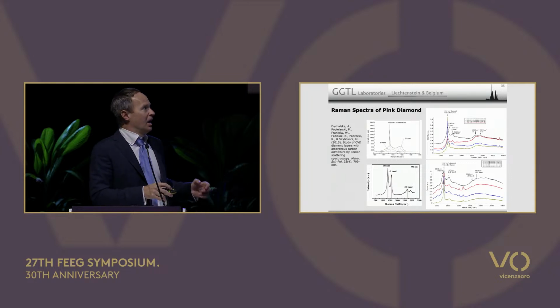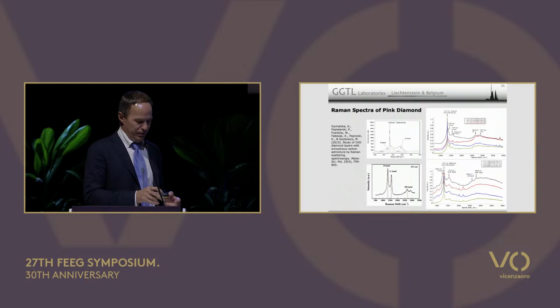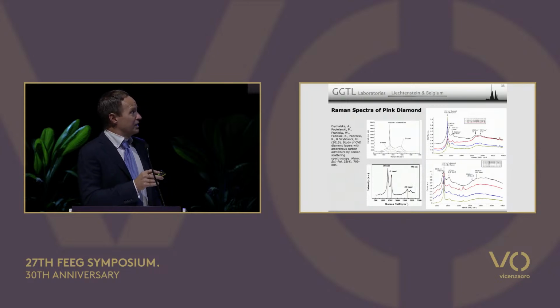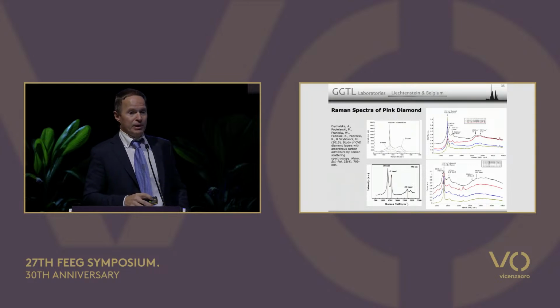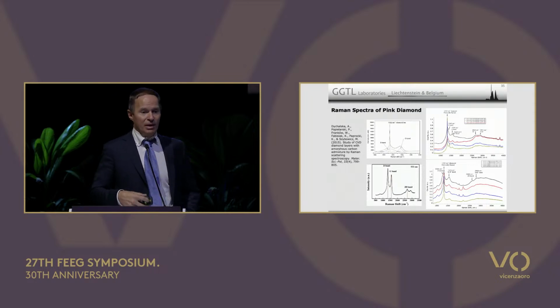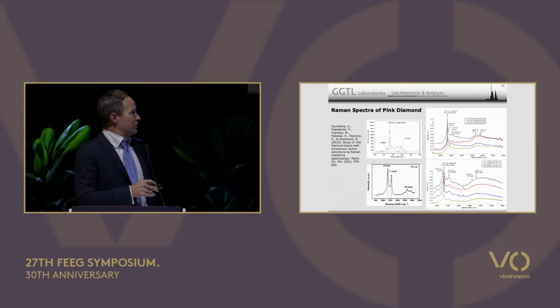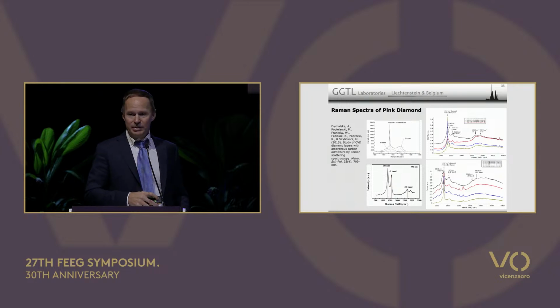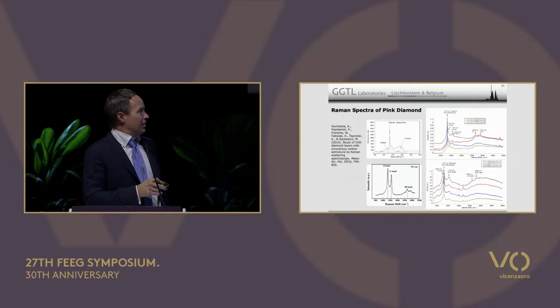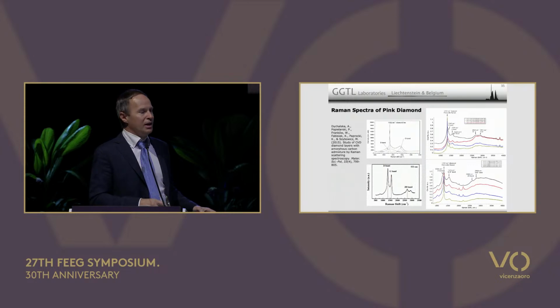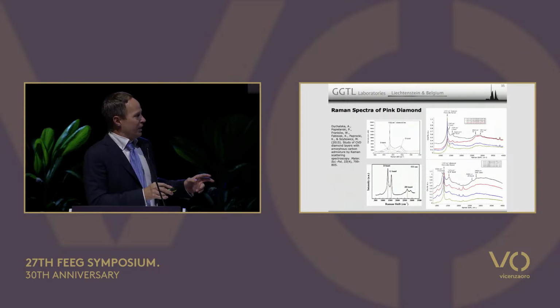Working through this and doing experiments at room temperature and low temperature, I came to the conclusion that what we're looking at here is not photoluminescence, but Raman signal. So these bands here and these bands here are not photoluminescence, they're Raman peaks. Looking through the literature, the thing they correlate directly to is graphitic carbon. So we're very likely looking at the influence of some amorphous carbon types being part of the defectiveness of these diamonds.